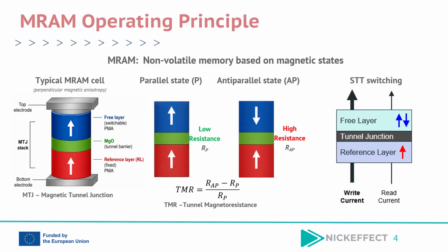The schematic on the right illustrates STT switching, currently the dominant commercial MRAM technology. As electrons pass through the reference layer, the current becomes spin polarized along the reference layer magnetization. The spin polarized current exerts spin transfer torque on the free layer and can switch its magnetization direction. One current direction favors the parallel state, while the opposite direction favors the antiparallel state. During readout, a much smaller sensing current is used to measure the resistance without disturbing the stored information.